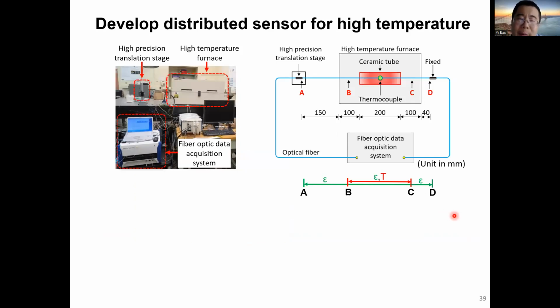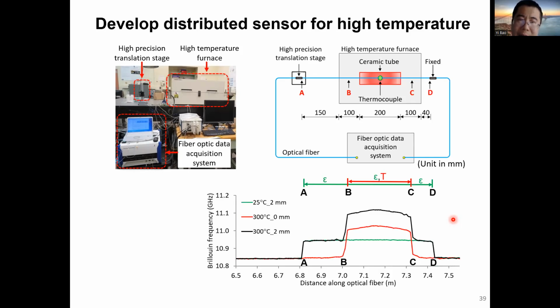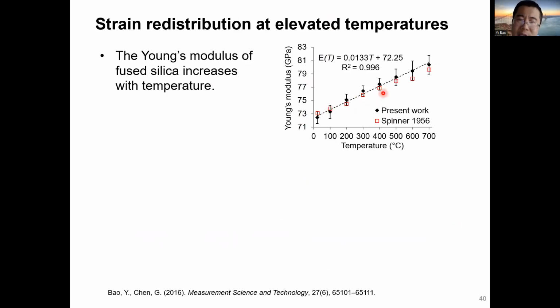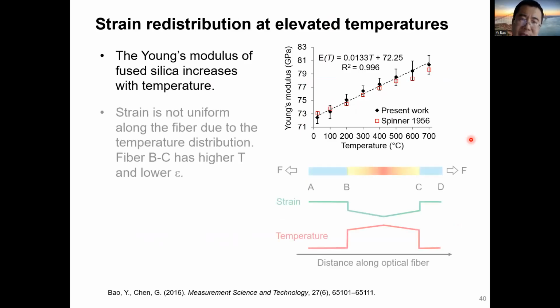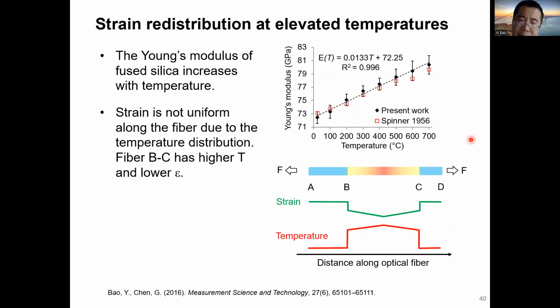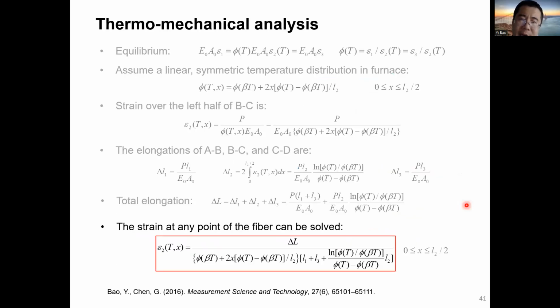So then I will briefly talk about our research on fiber optic sensors for high temperature applications. So we collaborated with engineers from National Institute of Standards and Technology to develop the high temperature fiber optic sensing technology. So one of the important findings from this project was that the Young's modulus of glass is dependent on temperature. See here, the Young's modulus increases with temperature, and this temperature-dependent property caused problems when we use the sensor in high-temperature applications because this generated non-uniform strain and temperature fields. So this affected the measurement accuracy.